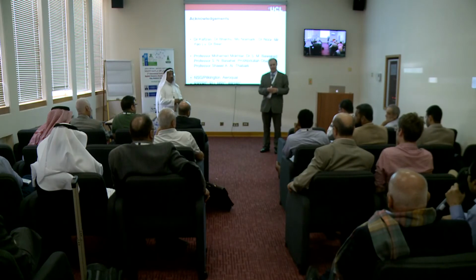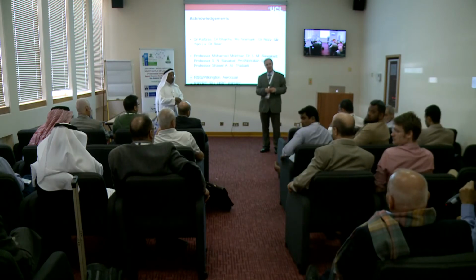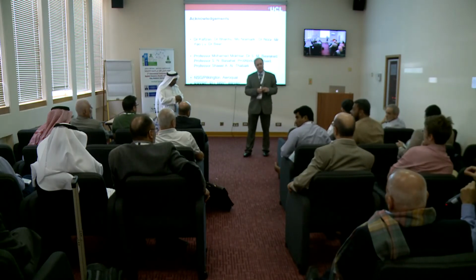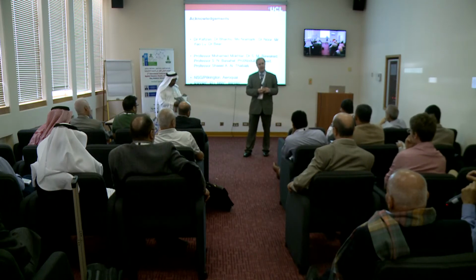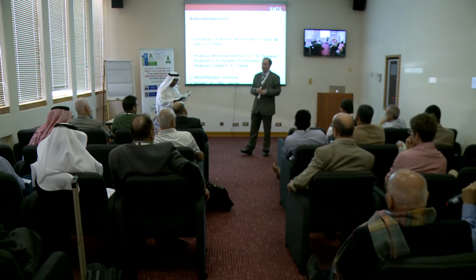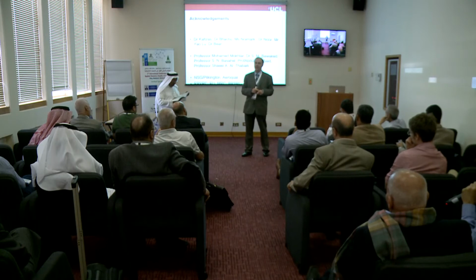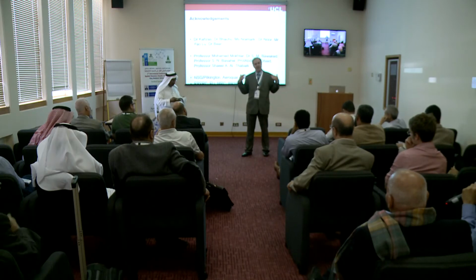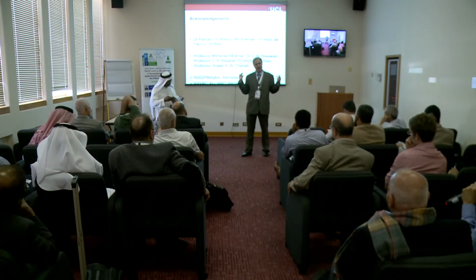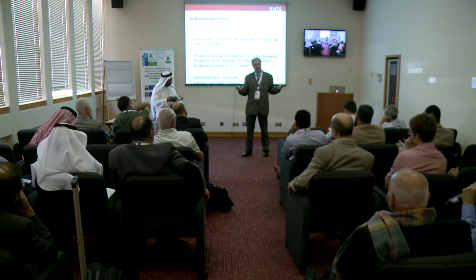My question is relevant to your water splitting part. What was the exact nature of your catalyst? Was it pure anatase and rutile, or was there some co-catalyst? We've had a 3-year project to try and come up with the best possible catalyst, so we've looked at a whole range. Typically for us, if it's titanium dioxide, an anatase rutile mixture works best.